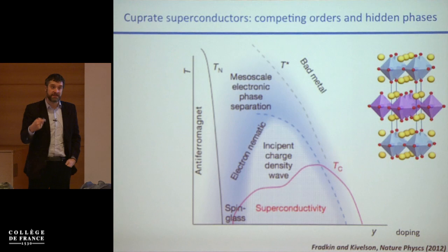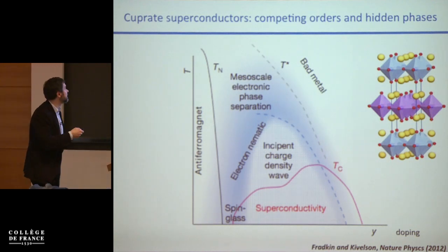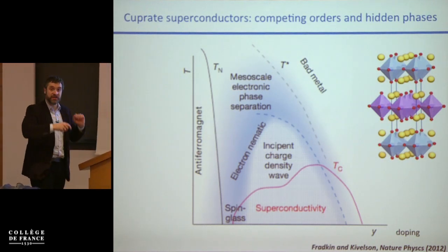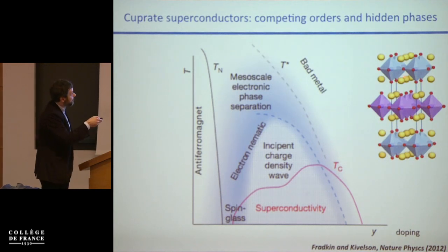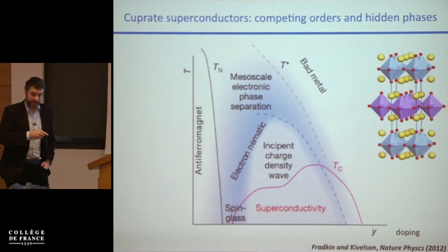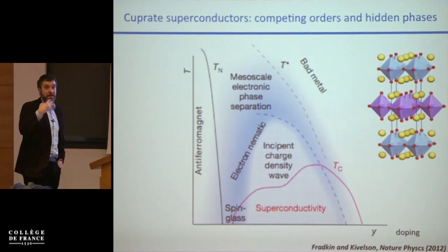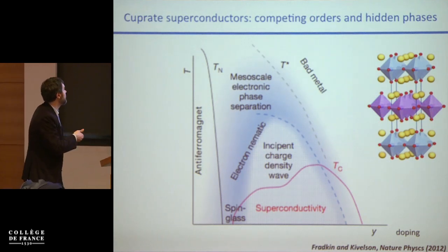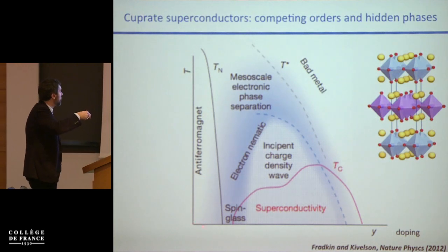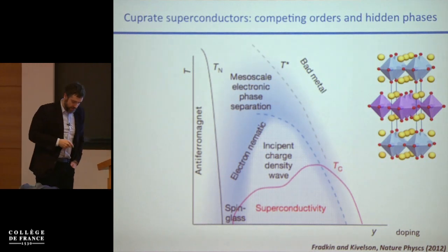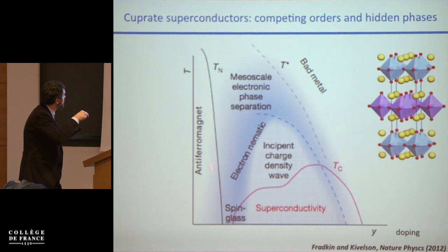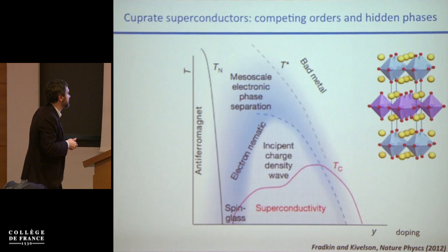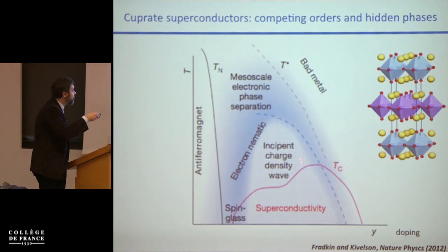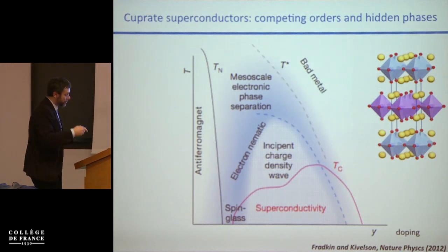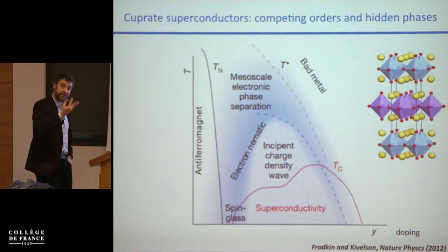So the cuprate superconductors, again, are these perovskite-like oxides in which copper atoms are hosted in oxygen octahedra. These copper atoms form planes, copper-oxygen planes, and the stoichiometry of the system is controlled by other dopants. And one can plot these phase diagrams that become more complex every time one looks in these papers. This is one incarnation of this. One has temperature here and the doping, which is the valence of the copper atom. For very small dopings, one has antiferromagnetic order, and at doping levels between, say, 5% and way beyond the 15% of optimal doping, one has this high temperature superconducting state that appears to be coexisting, competing or intertwined, etc., with other types of order that either help it or quench it.